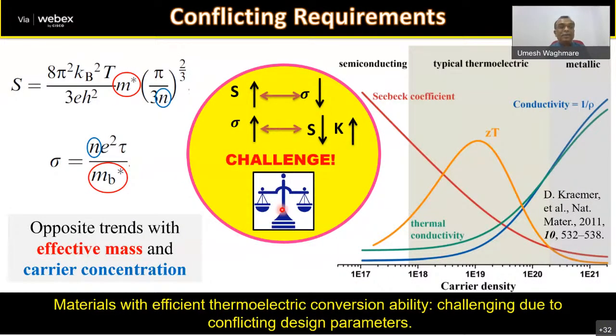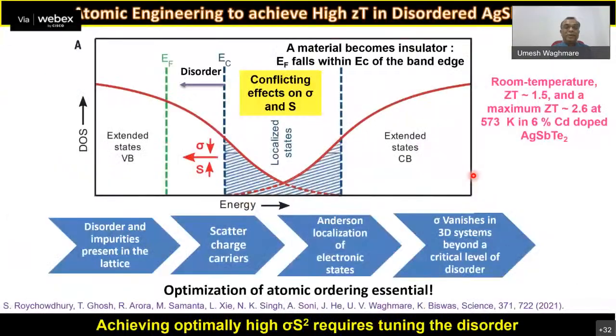So that's the scientific challenge. There are opposite trends that we need to meet, and this is typical of thermoelectrics. In low carrier density, one has a semiconductor with a high Seebeck coefficient, but it reduces notably. For a metal, you have high electrical conductivity, but the Seebeck coefficient reduces. So in between, you have a higher ZT, but that ZT may not be high enough for people to find it useful. So that's the science challenge of development of material, which we work on.